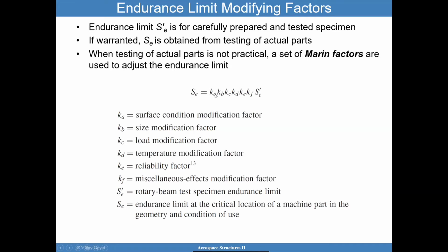Ka is called the surface condition modification factor. It depends on that surface condition. Kb is a size modification factor, as we discussed before. Larger sizes can affect your endurance limit. Kc is a load modification factor, so your test may have been done one way, but when you translate it to this SE value for your application, you may have to modify that. Kd is the temperature modification factor. Ke is a reliability factor if you want to account for reliability estimates, because I told you the SE prime is typically the mean value.